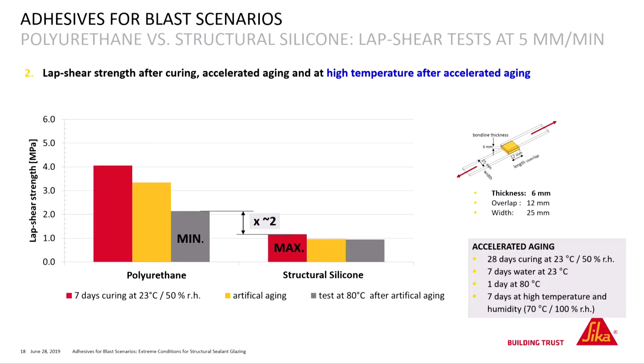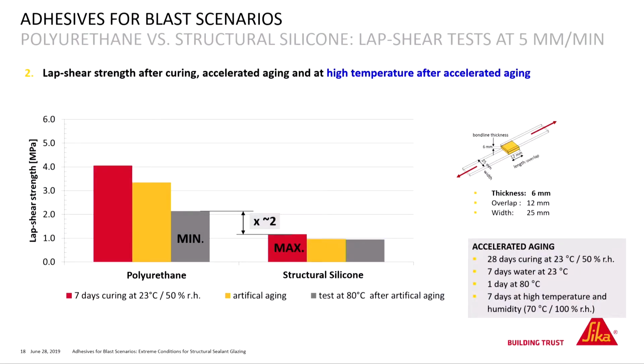Then let's come to high temperature behavior, and we did it even after accelerated aging. When you look at these bars, at the diagrams, if we compare the maximum we can achieve with silicone and the minimum at high temperature with polyurethane, it's still a factor of 2 higher than the silicone here. And this was measured at 6 millimeter thickness.